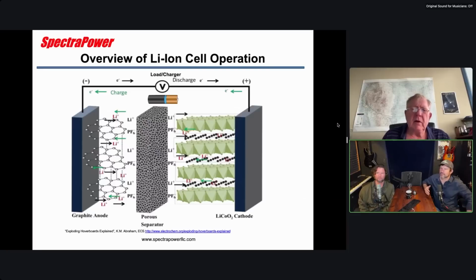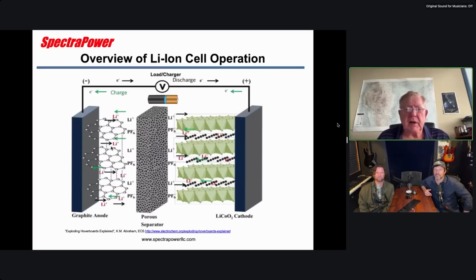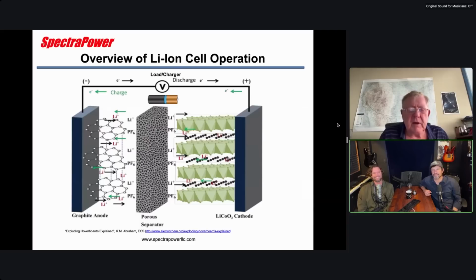You fold it or something, or how does it work? You coat it. You take this graphite powder and mix it into a slurry. Most people use water to make that because it's cheap. And when you make it, there's no lithium in it, so you don't have to worry about the water. When you coat the cathode, you use something called NMP, N-methylpyrrolidone, which is an expensive solvent, but because there's lithium in the cobalt, it doesn't react. Yeah. It's also volatile. It's hazardous and flammable. So you have to be careful about that.